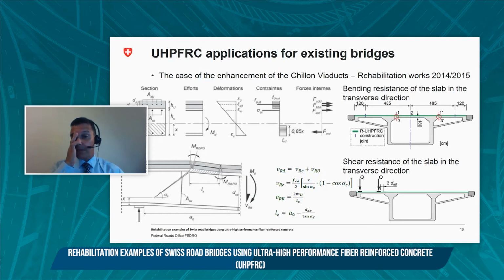Now, the deck slab of the viaduct does not have any shear reinforcement. Shear resistance of the concrete element is thus calculated as a combination of the concrete contribution and the contribution of the ultra-high performance fiber reinforced concrete. The contribution of the concrete depends on the concrete carrying the inclined compressive stress ahead of the crack tip and fails by crushing at the compression zone. So the contribution of the concrete depends on its compressive strength and the angle of the inclined shear crack.